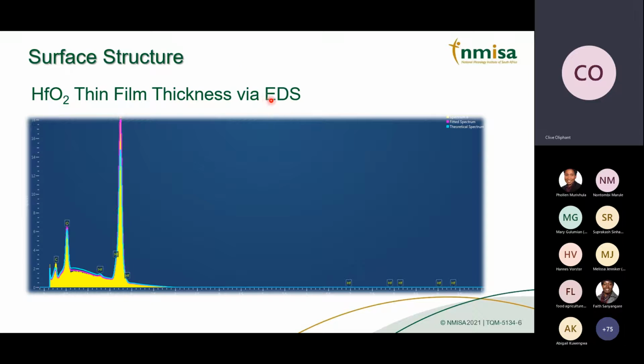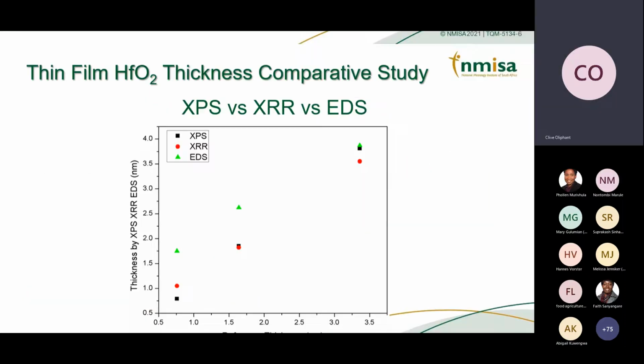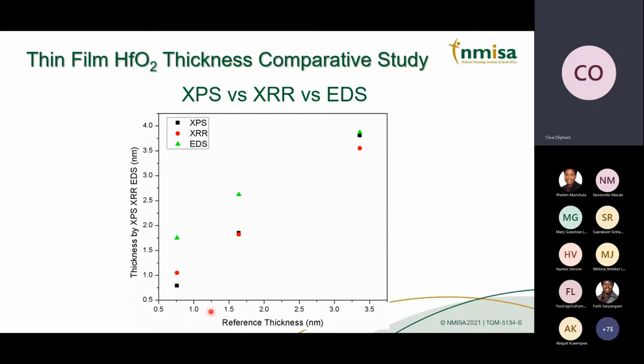However, we have been working on this EDS, which is a relatively accessible technique that has its limitations, but it can be used to extract the thickness of hafnium oxide. And we'll compare it against the internationally accepted XPS and XRR versions here in this slide. So here we can see, this is the reference thickness. It's quite thin, which is required nowadays for advanced microelectronics. XPS is the standard, which is these black cubes here.